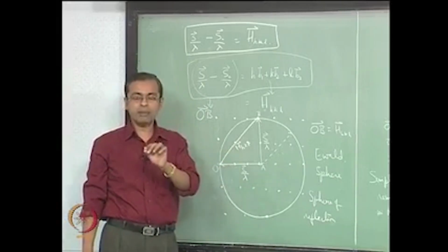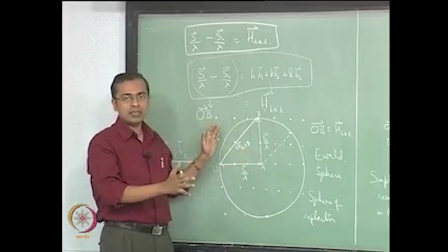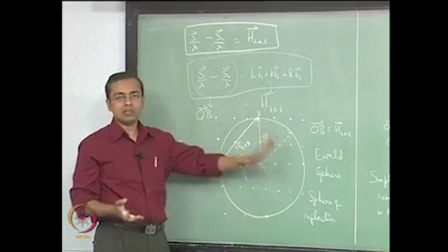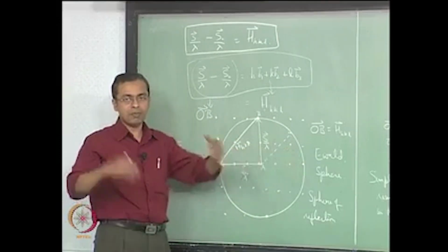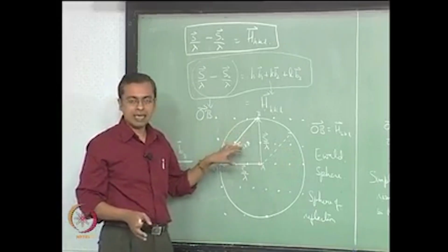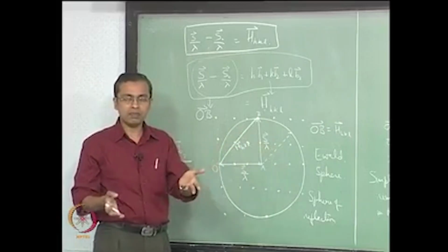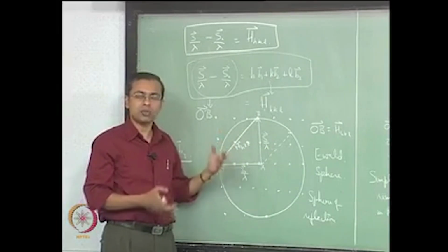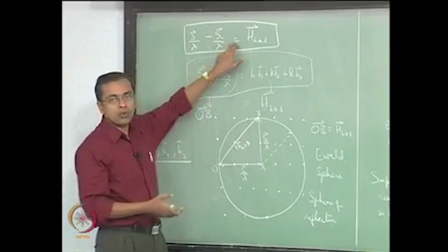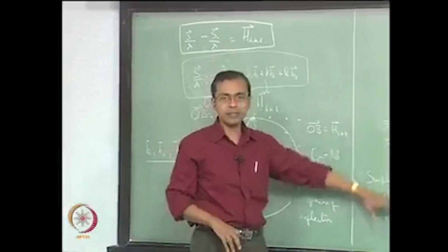It is now a simple cube of side 1 by A. So that is what will form the set of points here, and whatever wave we are talking of will independently form the sphere. So the sphere is independently formed based on the radiation you have chosen. The set of points that are there, which are reciprocal lattice points, are based on the material you have chosen, which happen to be simple cubic. Therefore the reciprocal lattice also happens to be simple cubic, and then you see the interaction based on this relationship, you know when diffraction will occur or when it will not occur. Okay, so this is with respect to simple cube.